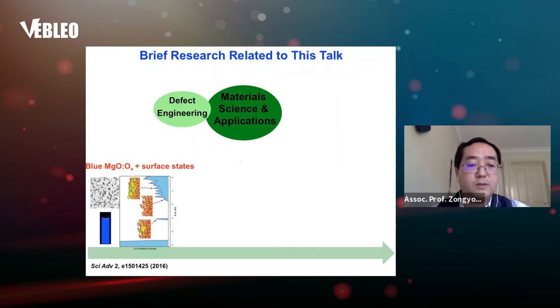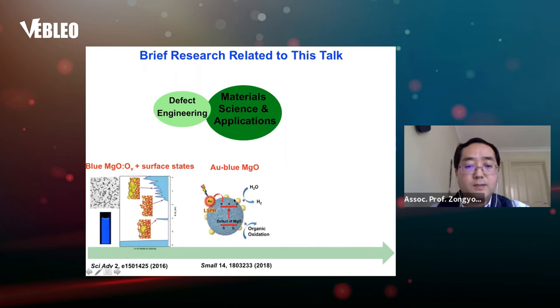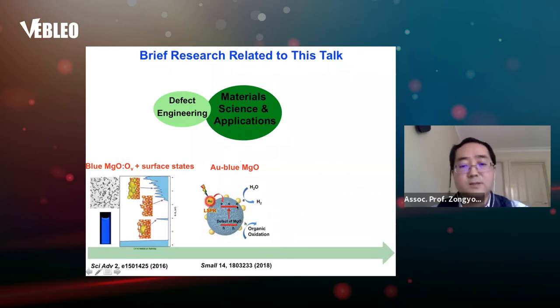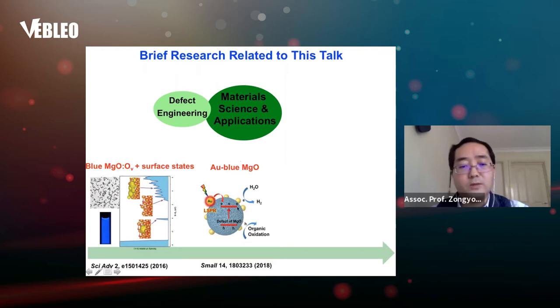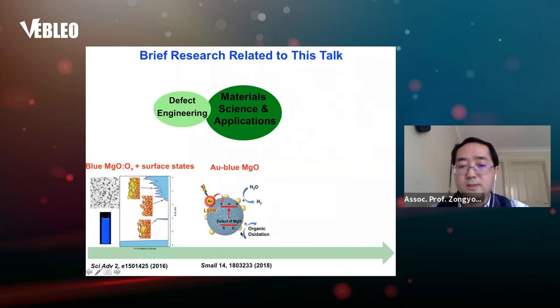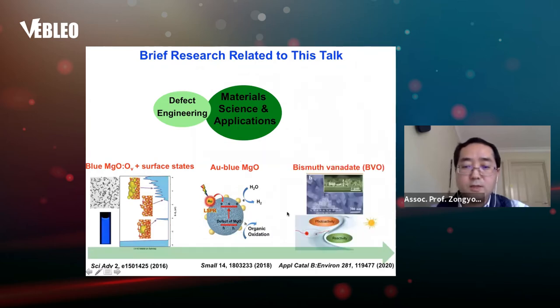Based on the stable MgO vacancy work, we asked: since MgO has vacancies and surface states, can we introduce plasmonic coupling? We studied the plasmonic coupling effect between plasmonics and the surface states and oxygen vacancies. We found very interesting results — performance in water splitting increased significantly and stability was excellent. This is because gold is always stable, and MgO is also stable since electrons do not go to the conduction band. The gold–MgO system is quite excellent for photosplitting reactions.